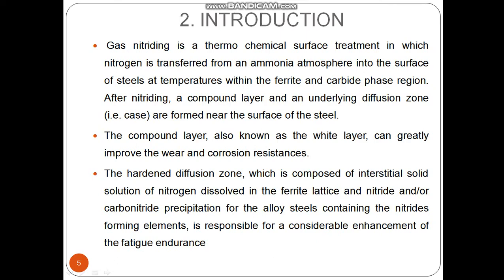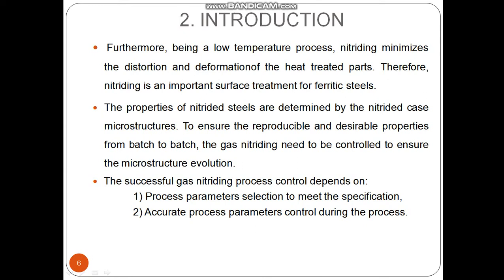interstitial solid solution of nitrogen dissolved in the ferrite lattice and nitride precipitates for the alloy steel containing nitride forming elements, is responsible for considerable enhancement of the fatigue endurance. Furthermore, being a low temperature process, nitriding minimizes the distortion and deformation of the heat treated parts. Therefore, nitriding is an important surface treatment for ferritic steels.